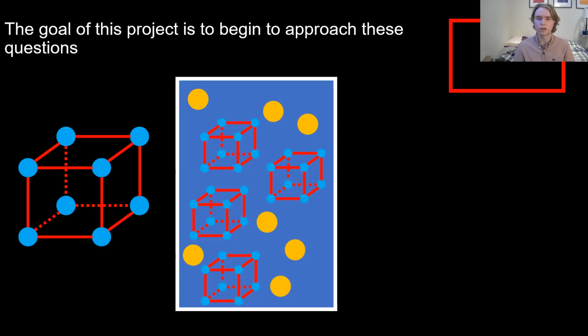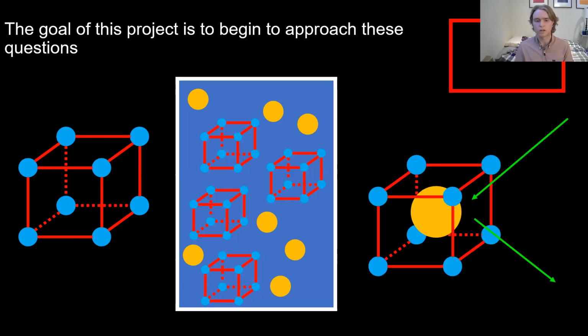From here, we could move to put the metal organic framework into a solution with EPR active molecules. Now, EPR stands for electron paramagnetic resonance, and I'm going to get more in depth on what EPR is a little bit later. But for now, just know that these EPR active molecules are active to the instrument, EPR, and that's very important because once these molecules have been incorporated into the framework, we can actually begin to use EPR to selectively look at these molecules, ignoring the rest of the framework. And the great thing about EPR is that it can be used quantitatively. So in this case, we would be looking to actually count the number of molecules that have been incorporated into the framework after a given amount of time. And that would be really useful for answering some of these questions we want to be looking at.